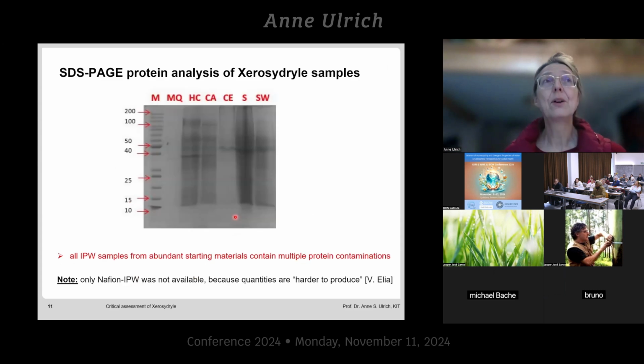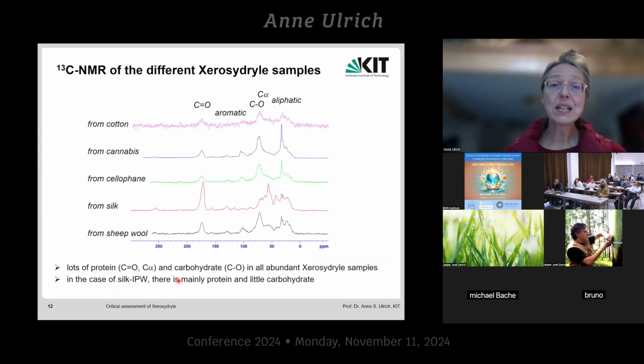And so to be sure, we did a protein analysis on SDS polyacrylamide gel of the many different Xerosydryle samples we had received. And this is a molecular weight ladder, which allows you to look whether there's any protein present in the sample, which gets stained. And in fact, all the abundant samples had multiple protein contaminations, many bands. So yes, there is definitely a lot of protein in there and not just H2O. Interestingly, only the Nafion sample was not available because it is so hard to produce and they did not have much material for us. So let's look at the NMR again.